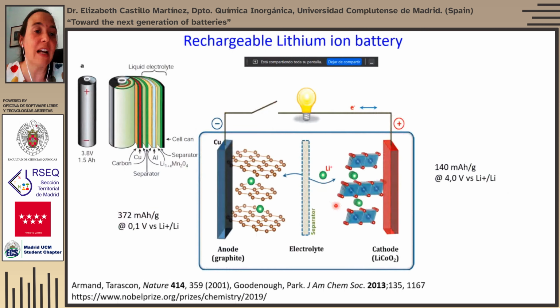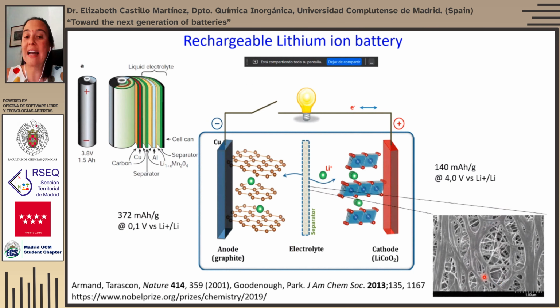So if we were to look at one of these cylindrical batteries from inside, we will see that they actually consist of a roll of many thin films stacked one on top of each other. These thin films will be a copper anode current collector, then the active material, the anode itself, which in the case of commercial lithium-ion batteries is graphite intercalated with lithium, then a polymeric separator, which has a microporous structure, and it's designed so that if the temperature rises because of some short circuit event, the pores close, and then the short circuit can be stopped. Then the layer of cathode material, which in the first commercial lithium-ion batteries was lithium cobalt oxide, and then the aluminum current collector on the cathode.